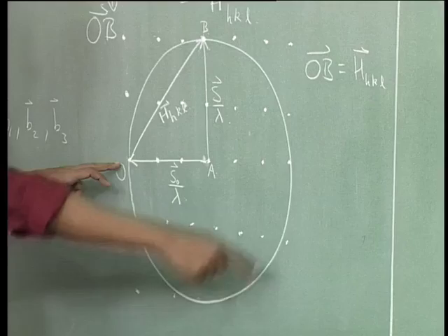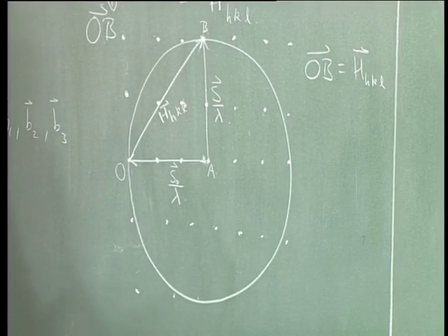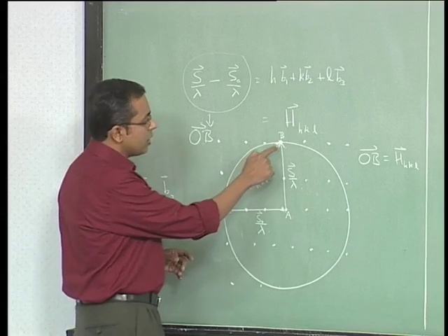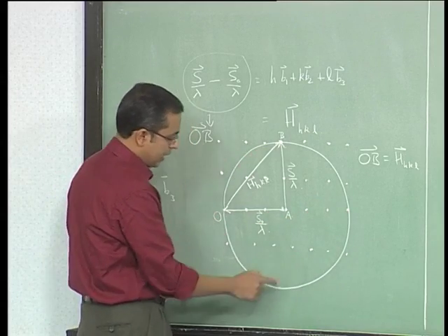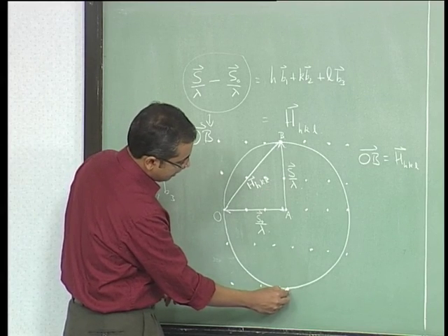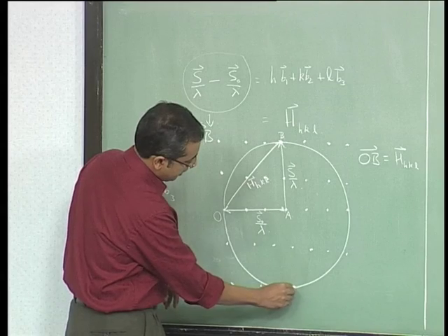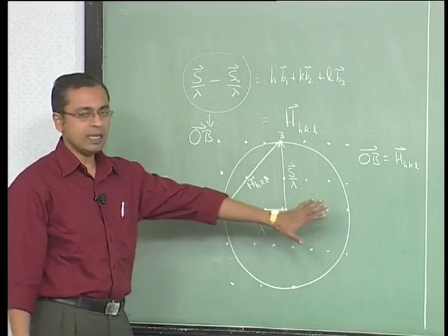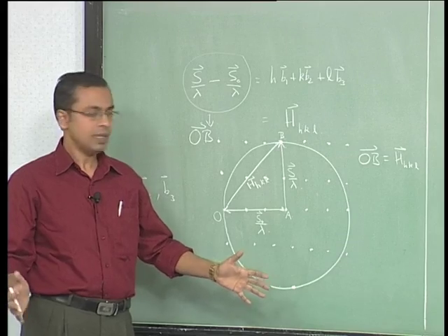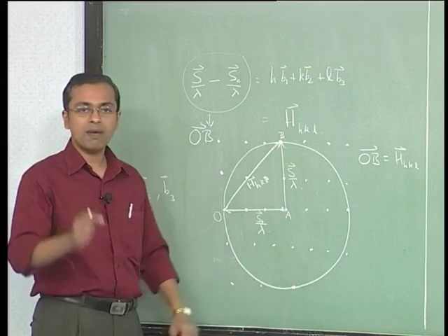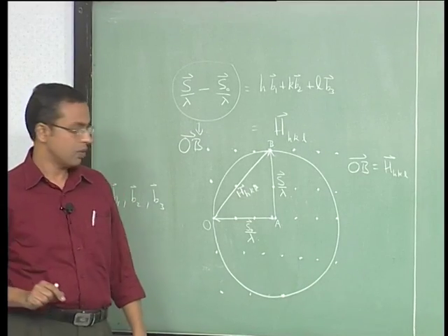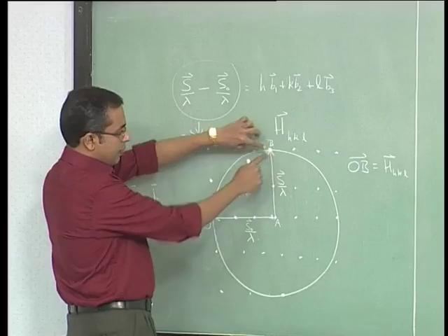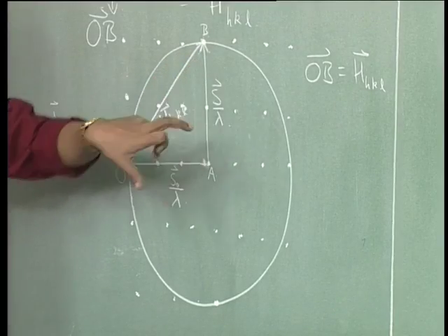So this circle that we have drawn is a circle drawn in reciprocal space, okay. In general it is in reciprocal space. At particular locations it is also touching valid reciprocal lattice points. In this case, for example, by symmetry somewhere down here, if you draw it correctly, there is a point where it will touch the reciprocal lattice point. So this circle is independently existing in reciprocal space, and at particular locations it happens to touch valid reciprocal lattice points, okay. And therefore at those particular locations you can now define that wave vector S by lambda